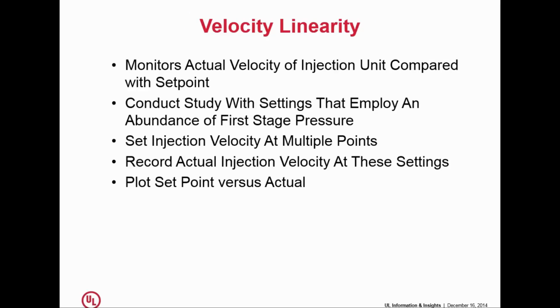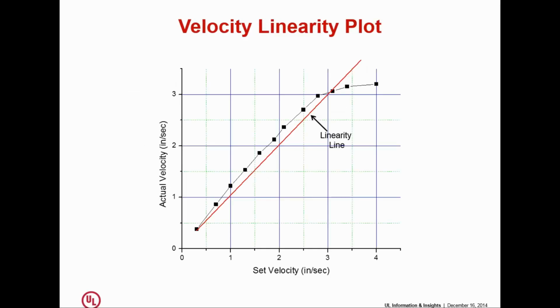The other thing is velocity linearity. When you look at a machine setting and you plug in and you say, go 40 millimeters a second, don't take it for granted that the machine is actually doing what you told it to do, because when you get up into the higher realms of what the machine's capabilities are, you're going to find out that it can't necessarily do what you're telling it to do. And so there's a study you're supposed to do where you basically set the injection velocity at different points and then actually record the velocity you actually get.